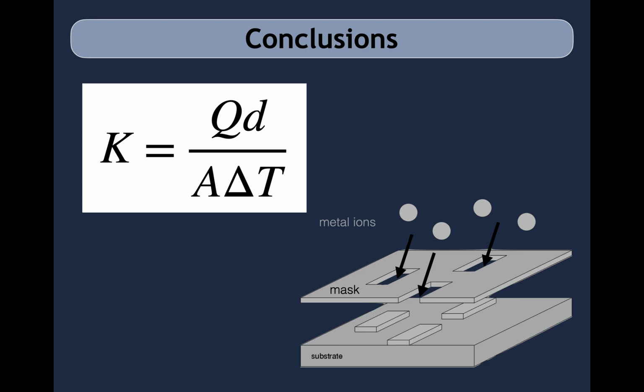We know that the thermal conductivity of a sample is a function of the applied heat, the distance between the measurement points, the area of the sample, and our measured change in temperature. Knowing the geometry of the silicon nitride suspended platforms and connecting bridge, we have developed a fully repeatable method to measure and control the applied heat, and therefore delta T, across the suspended silicon nitride bridge.